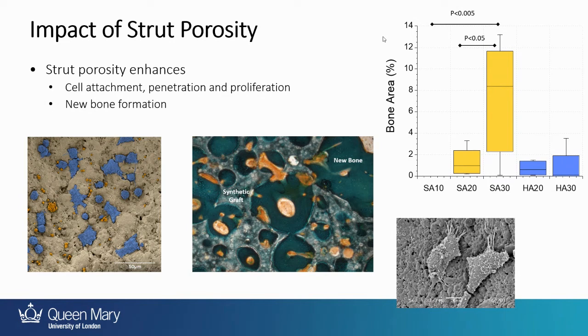So we found by increasing the strut porosity up to sort of levels of 30% or 40%, we were able to get our materials to behave like it was a growth factor, effectively. So it's a dead, inanimate piece of material, but it's influencing the response from the local host tissue to act like it was an inductive material.